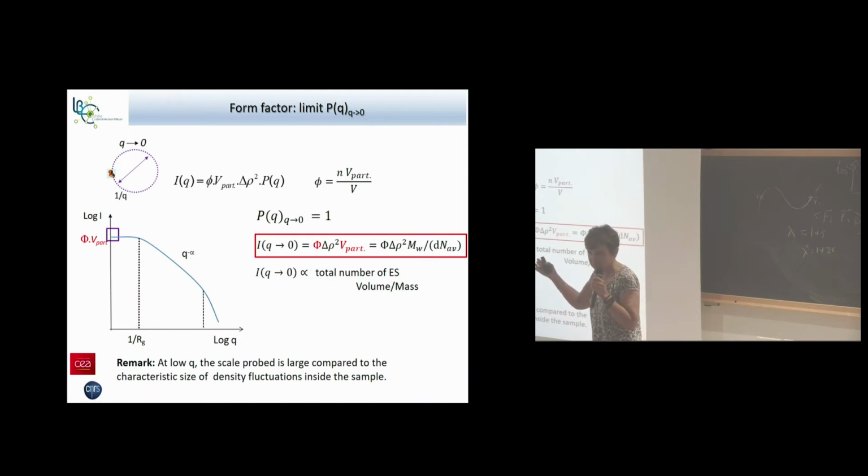So to measure the incident flux, we need to attenuate the beam or to use another detector which is not as sensitive as the detector used to record the scattering intensity. But then we have to calibrate this extra detector. With X-ray, it's a bit more difficult, but it is possible. With neutrons, it's much easier, so it's done.